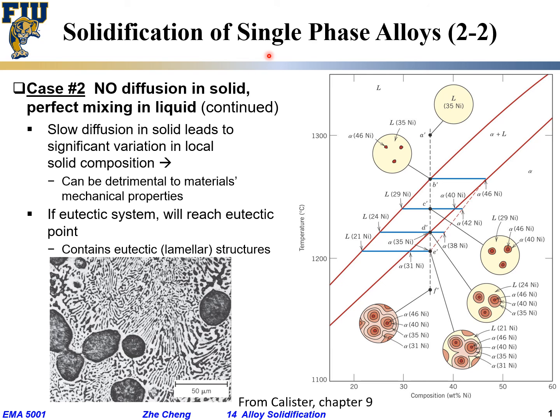That's the consequence when we move away from equilibrium — from very slow cooling to reasonably fast cooling — assuming stirring within the liquid to keep liquid composition uniform, but no diffusion in the solid. Within a few hours diffusion only happens on the micron scale, but these microstructures are often hundreds of microns, millimeters, or even centimeter scale. For large ingot solidification we're talking millimeter or centimeter scale, so you can essentially treat it as no diffusion in solid.